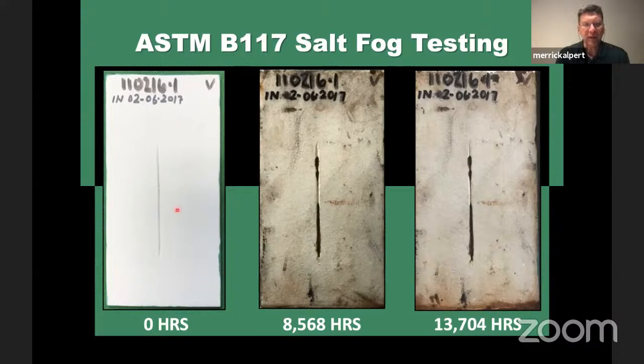We start with a new panel, and then we cut the scribe line in it. With Eon Coat, you have to make certain that you cut through both the outer ceramic layer and the passivation layer. How do we know we got all the way to the steel itself? Because at 8,568 hours, about 1 year, you can see what's going on. Now, most importantly, if you look here, what do you not see? Well, you don't see the scribe growth or scribe creep. You don't see underscribe. You don't see the bubbling that you would see with traditional paint.